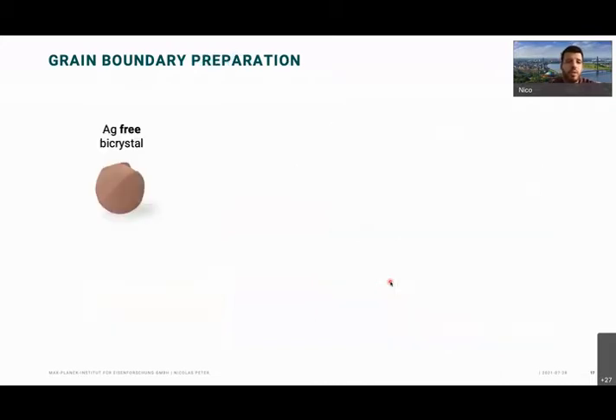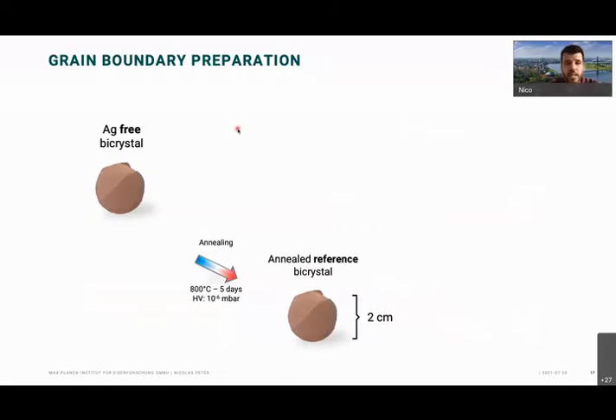So from this bicrystal, I cut some pieces, some cross sections, and used 3 different states to then observe and make my research on what is happening. So first of all, we have a silver-free bicrystal, and this is a cross section through the bicrystal. We then take one of these and just anneal it for very long, 5 days at 800 degrees C and under high vacuum, 10 to the minus 6 millibars, which is the annealed reference state, so to say.